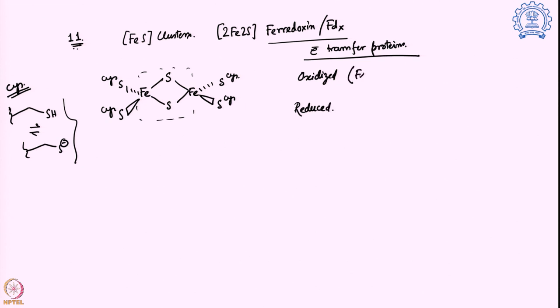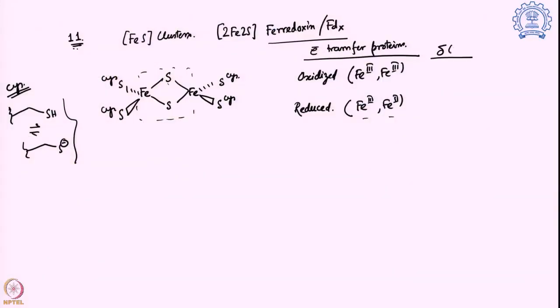And we found in oxidized state it remained in iron 3, and these are the proteins which typically exchange only one electron. So, the reduced state will be iron 3 iron 2. Now, the question is, over here iron 3 and iron 2, I have 2 sulfides bridging ligand, am I going to see a mixed valence system or they will be localized? So, for that we looked into the Mössbauer spectra for this system. And what we found in the oxidized state, the value of isomer shift is 0.27, and quadrupolar splitting value is 0.6.